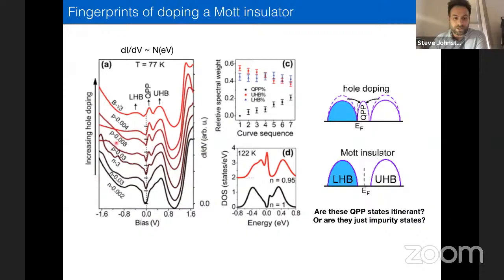The state that you're seeing here at about minus 1.6 eV, this is a silicon band. The silicon gap would be covering from here to here on the 111 surface, and then this would be the first unoccupied silicon band in the substrate itself. The stuff in the middle here, these are the tin monolayers. Okay, so this is the lower Hubbard band. This is the gap, and this is the upper Hubbard band. And this is consistent with what the Werner-Hanke paper saw with the photoemission results, that you get this gap forming and spectral weight above and below the Fermi energy.